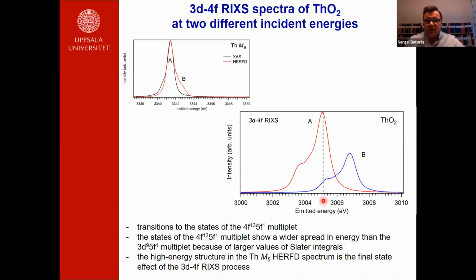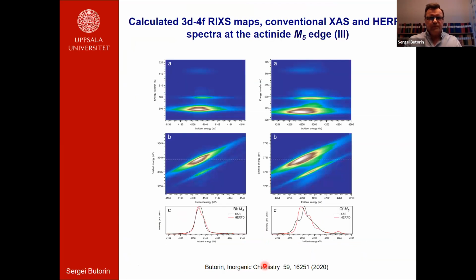We can see that for the emitted energy of the HERFD cut through the maximum of the RIXS intensity on the RIXS map, we still see that spectrum B has some contribution with some intensity. And this spectrum actually consists of transitions to the 4f13 5f1 multiplet. This multiplet has a larger energy spread due to larger values of Slater integrals. So it means that the appearance of this high energy structure is actually a final state effect of the 3d4f RIXS process. The calculations actually show quite a large difference for californium dioxide between the HERFD spectrum and the XAS spectrum for M5.